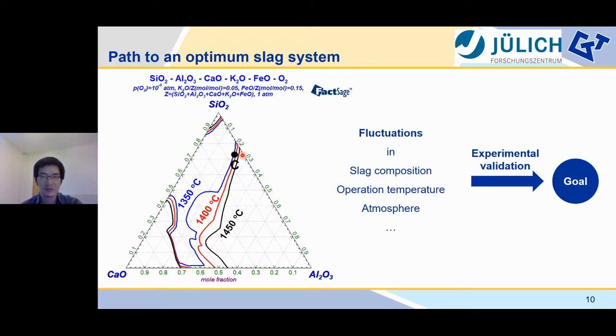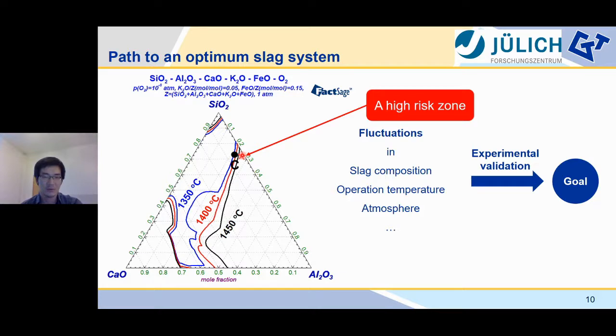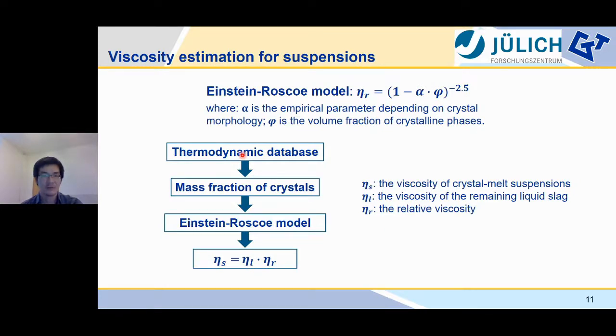We can turn to the second part concerning the viscosity of the suspension system, because this is also very common during the operation of entrained flow gasification. How to estimate the viscosity contribution from the crystalline phases? Here we use the Einstein-Roscoe equation to derive the relative viscosity, and then further multiply the viscosity of the remaining liquid slag to get the suspension viscosity. By doing this, we use FactSage with the proper database to calculate the mass fraction of the crystals. Here we assume that mass fraction is equal to the volume fraction — that's fine for the first rough estimation.